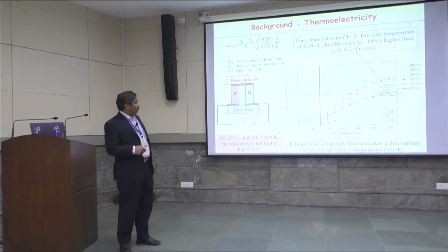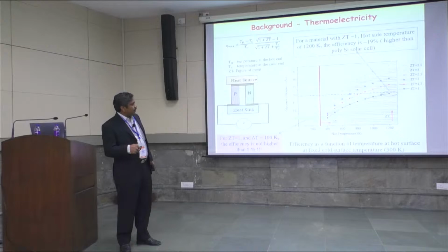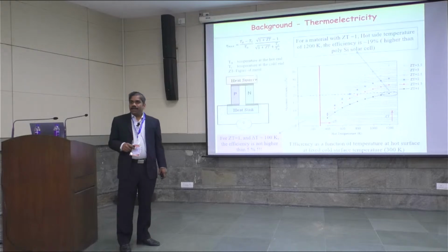And this is the conversion efficiency, which is theoretically calculated from the relation between the input energy and output power. And this has been calculated based on two factors. One is the hot end temperature of a thermoelectric device, and another is the ZT of the material. And look at this, this is the theoretically calculated data. I just drew one more dotted line, parallel to the x-axis. And this is the typical conversion efficiency of a silicon solar cell at the industrial scale. So if you want to increase the efficiency up to this level, then your material should withstand up to 1200 Kelvin, right? But at the same time, a lot of materials are available.